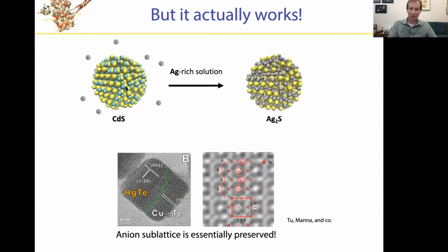Moreover, the full pipe dream has essentially been realized in the sense that the anions hardly moved. This lattice was preserved, and you can see that strikingly in electron micrographs that show you, in the case of a different material, how the incoming material has intruded. And you can see the distinction in their lattice structure. You can really map out in an incredible feat of imaging where the ions are and find that in some sense, the anions in the structure basically looked away for a moment and found all of their neighbors had transplanted.